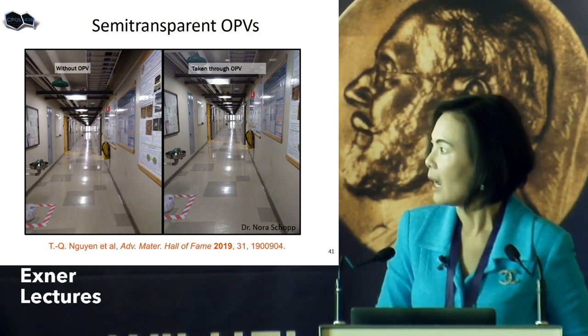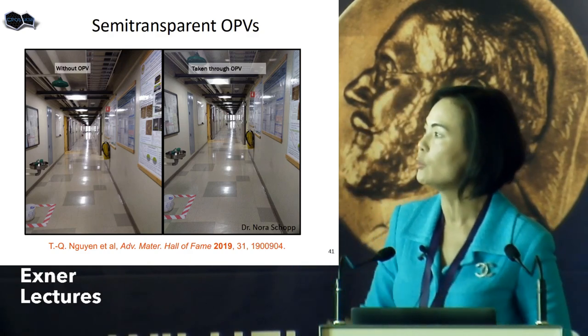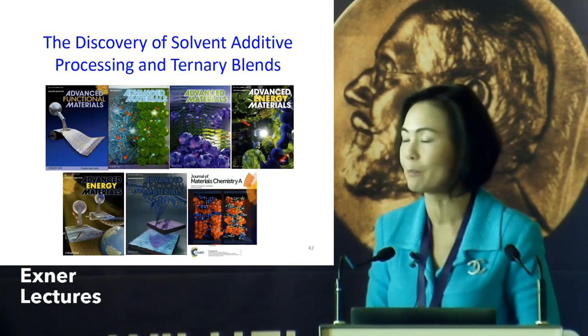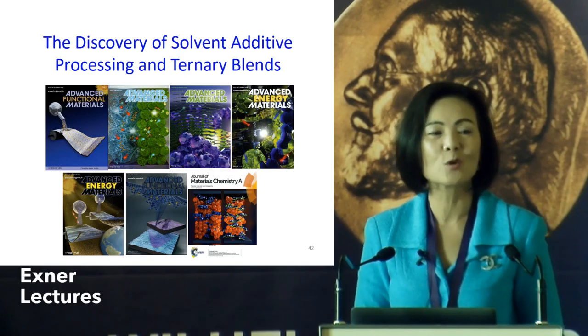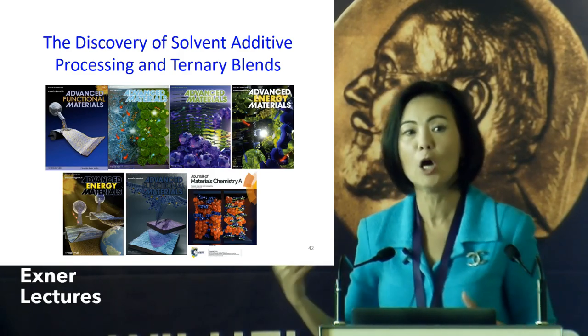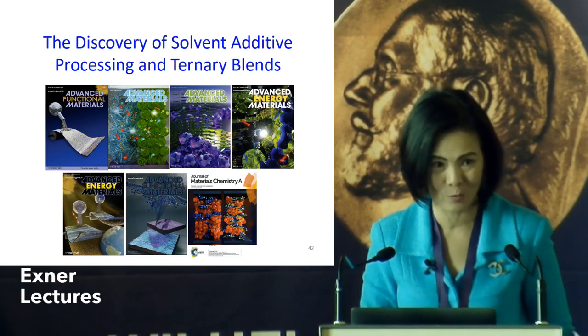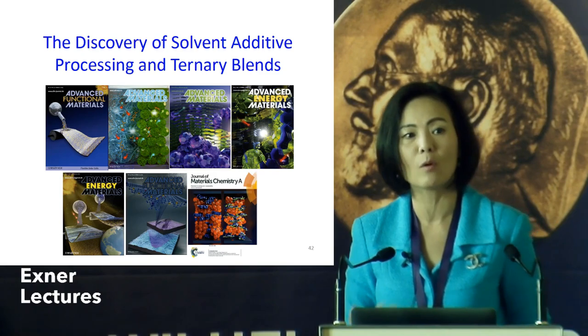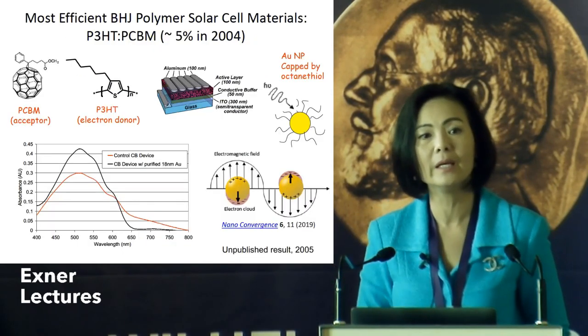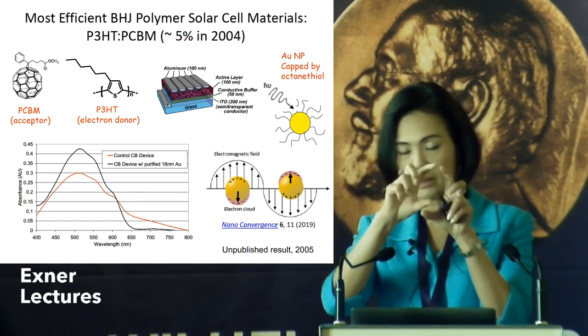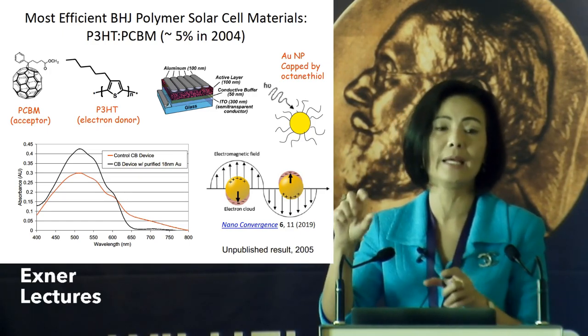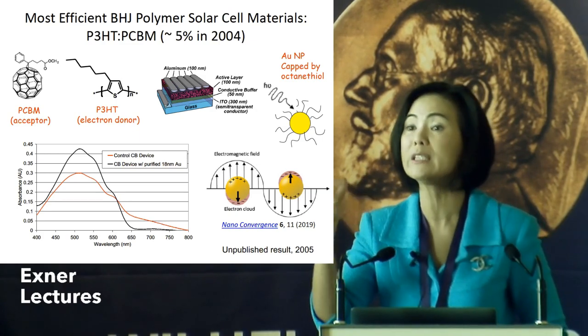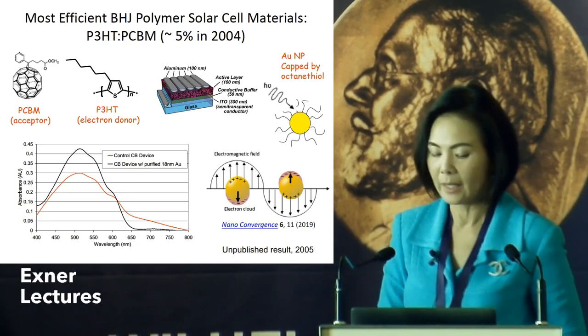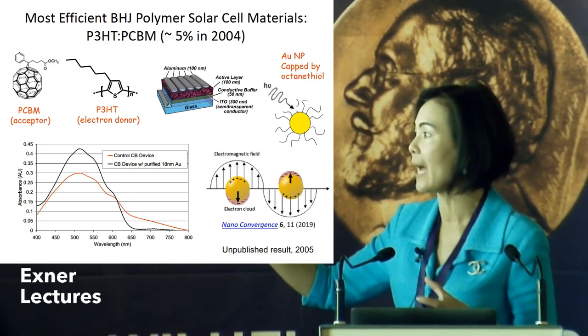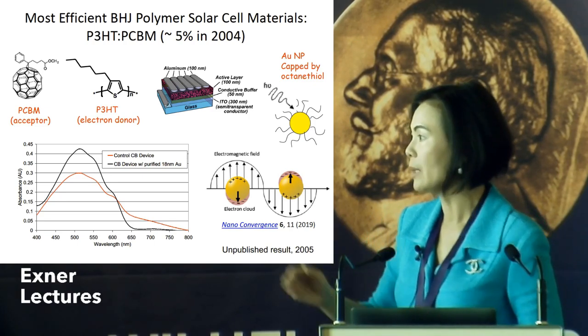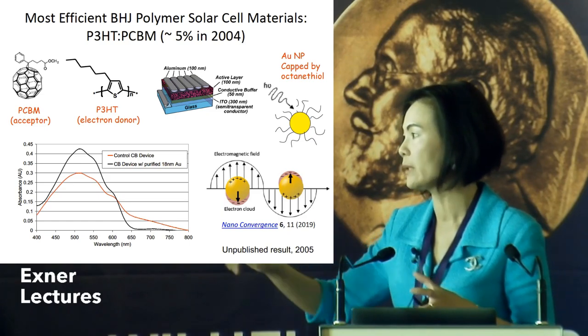Yeah. And then another contribution to the field is the discovery of solvent additive processing and also ternary blends. Many people now use it routinely, but didn't know the story behind it. How did we discover this? So for my postdoc, I came from Lou Brus's group, and he worked with gold nanoparticles. And back then, even until this day, the organic solar cell active layer is very thin, about 100 to 120 nanometers thick. So the idea we were thinking was, if I can blend gold nanoparticles into the active layer of the solar cells, and because the gold nanoparticle is 10, 15, 20 nanometers, when you shine light on that,